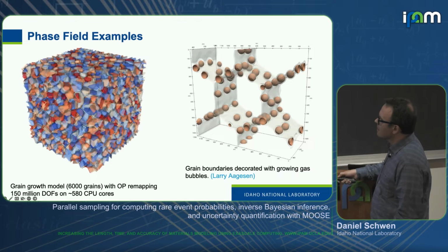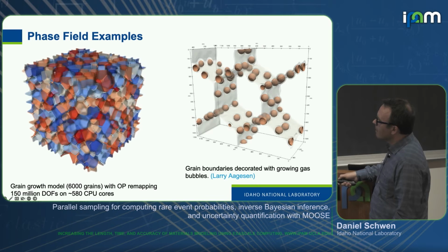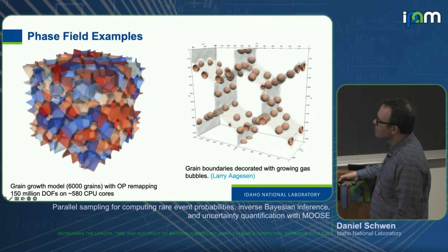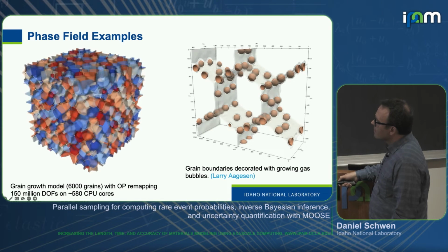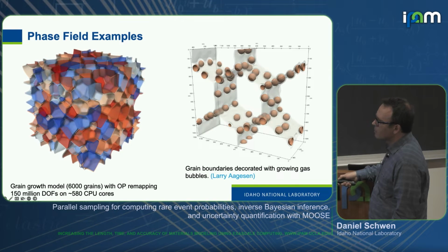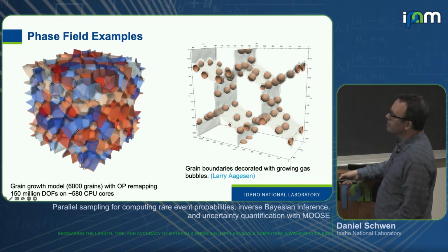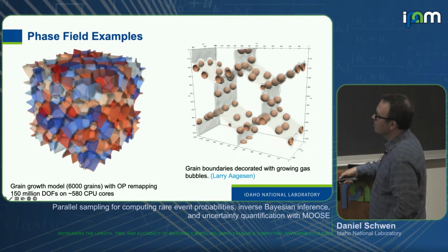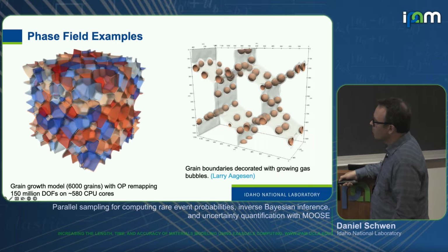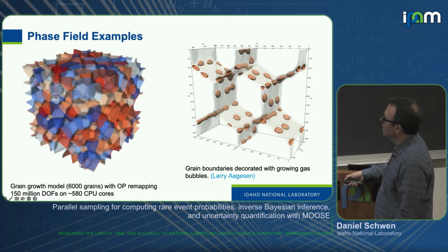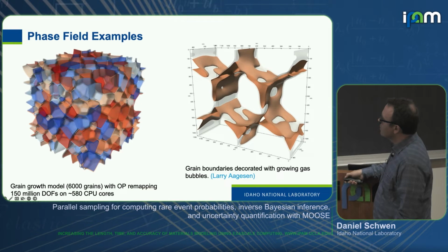Just some cool-looking examples. This is a grain growth simulation, 6,000 grains in 3D, using an order parameter remapping mechanism. You can see those grains are changing color here. That's because we're only using 10 or 15 order parameters to map onto the grains. So not every grain has its own order parameter, but if two grains are far apart, you can reuse order parameters and dynamically remap them. This is a simulation of 150 million degrees of freedom on 580 CPU cores. This is a simulation looking at percolation or fission gas coverage on grain boundaries from my colleague Larry Aagesen.